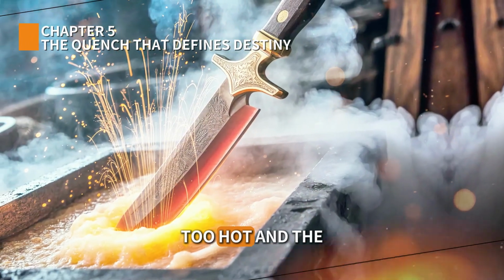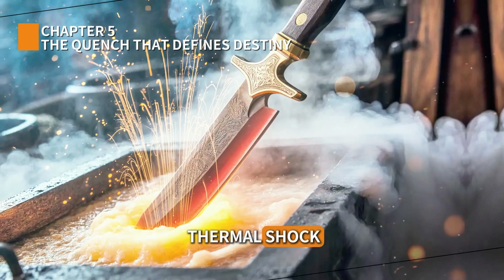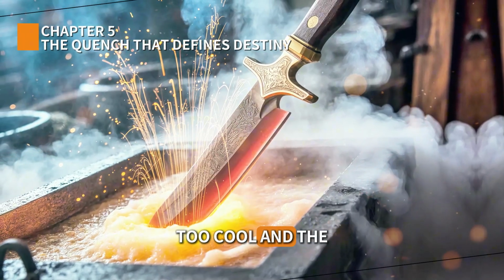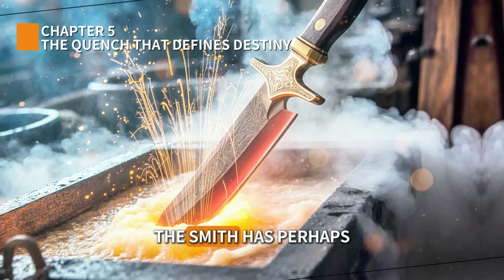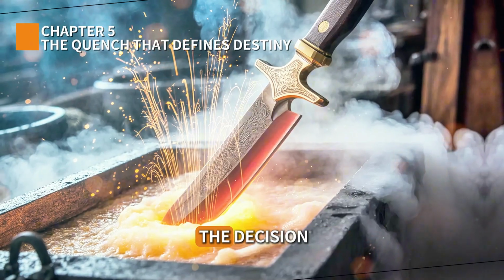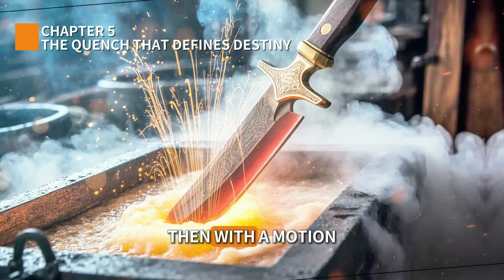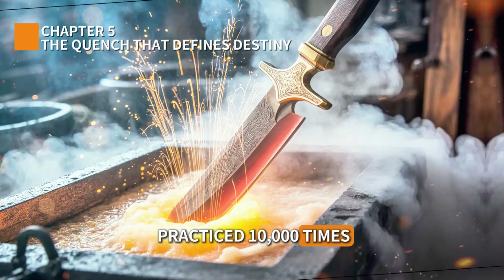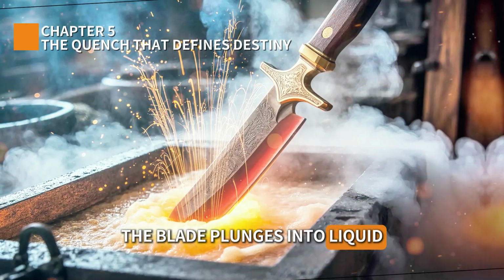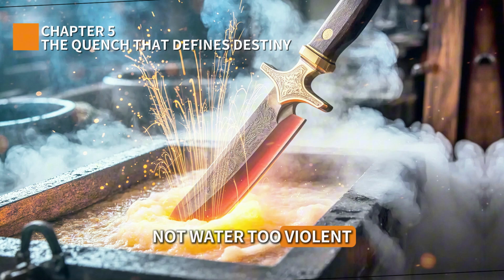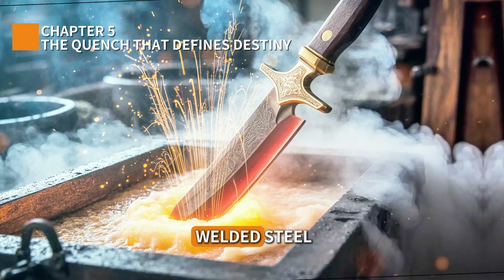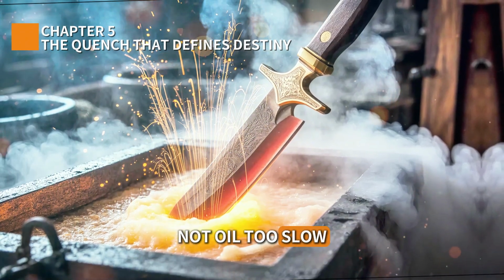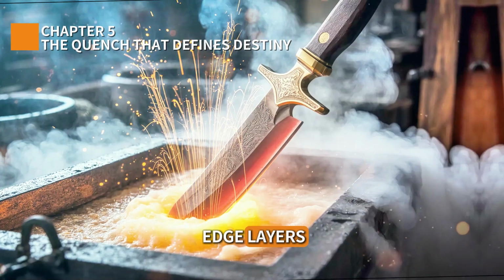Too hot, and the blade will crack from thermal shock. Too cool, and the steel won't harden. The smith has perhaps 3 seconds to make the decision. Then, with a motion practiced 10,000 times, the blade plunges into liquid. Not water, too violent, it would shatter pattern-welded steel. Not oil, too slow for the high carbon edge layers.